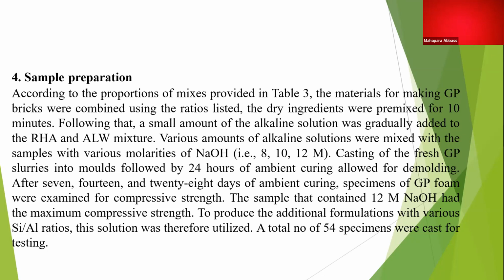The molarity of sodium hydroxide was kept as 8 molar, 10 molar, and 12 molar. The main combination here is that we have to keep the silica to alumina ratio from 1 to 3, because if there is a good proportion between silica and alumina, then the chances of formation of aluminosilicate hydrate in geopolymer concrete are very good. So we are providing 3 ratios here: silica to alumina of 1, 2, and 3.